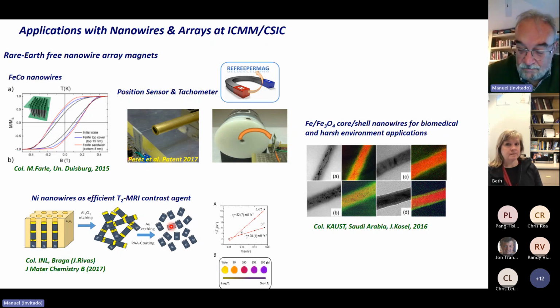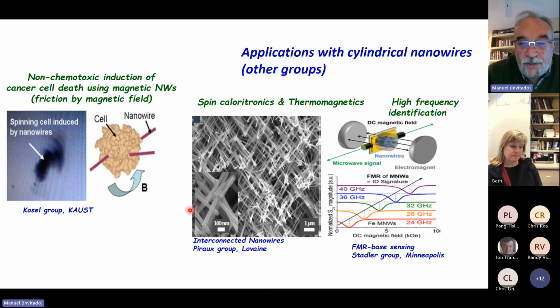We got nickel segments that are kind of nanoparticles with a determined preferred direction. So it's somehow different from nanoparticles because they have a non-spherical geometry. And they have proved that these segments of nickel are very interesting as magnetic resonance imaging contrast agents. Also, I would like to mention other applications. There are several groups. One of them is, I think, Beth Stadler. This is the last application I know from her group, on high frequency identification.